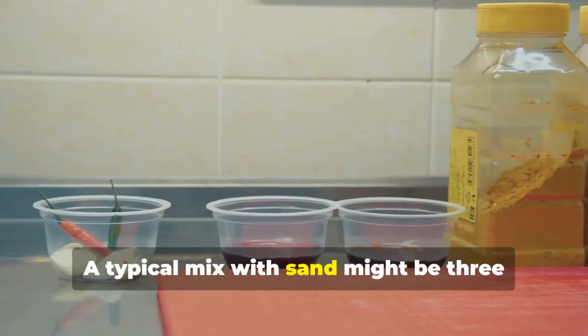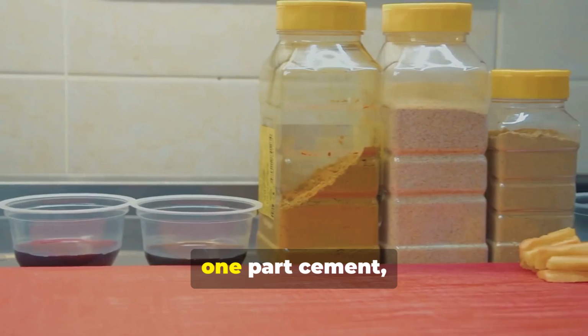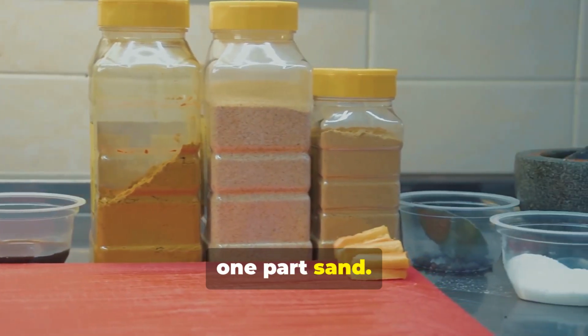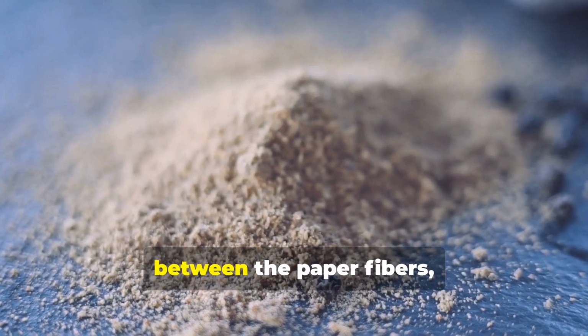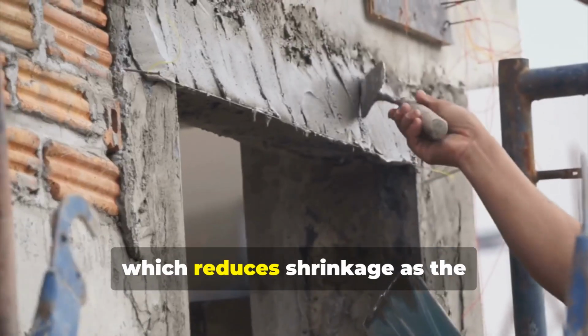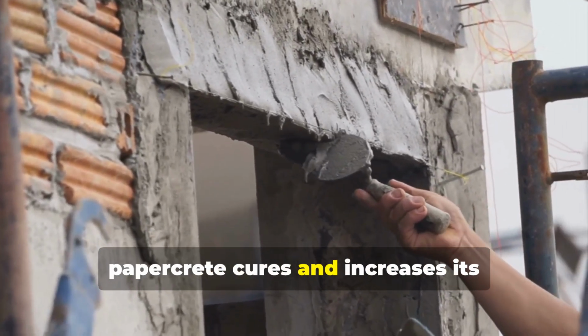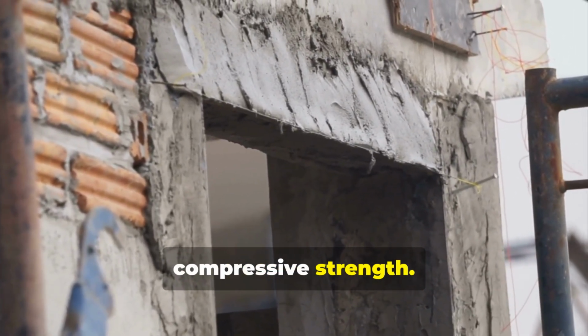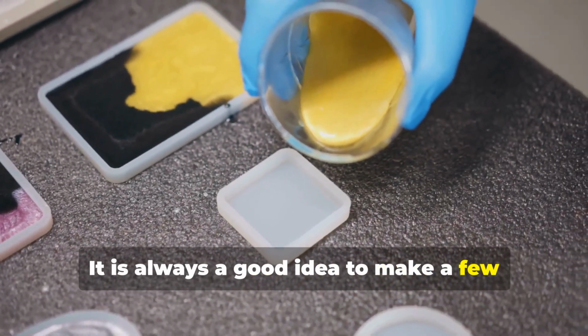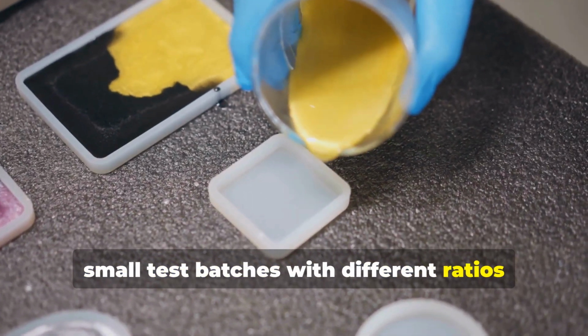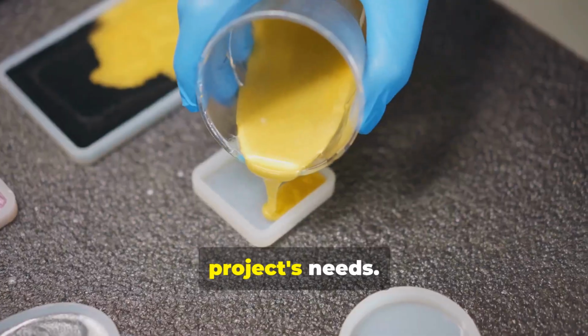A typical mix with sand might be 3 parts pulp, 1 part cement, 1 part sand. The sand helps to fill the voids between the paper fibers, which reduces shrinkage as the papercrete cures and increases its compressive strength. It is always a good idea to make a few small test batches with different ratios to see which one best suits your project's needs.